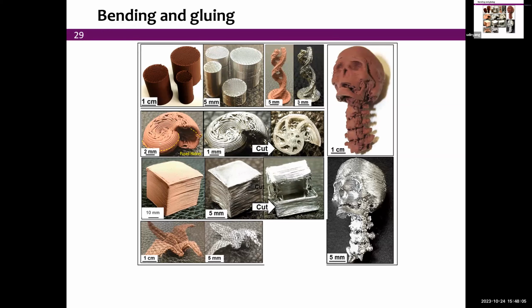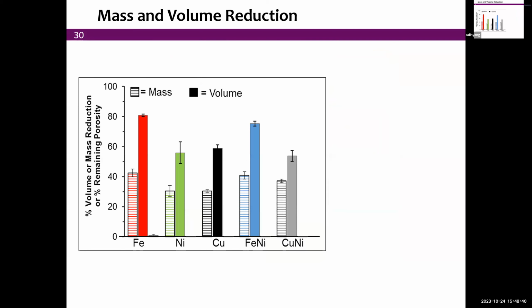And I promised already the origami, so this is the unavoidable crane that we can make from sheets that are then, in that case, folded by hand. But that's really feasible if your polymer, you can choose it, is flexible enough for that kind of work. And you can actually also print two pieces separately and then merge them using a little bit of solvent, and then do the full sintering on multiple pieces that have been welded or glued, if you want, with a bit of solvent. So it's very nicely flexible in terms of the many design structures that we can make.